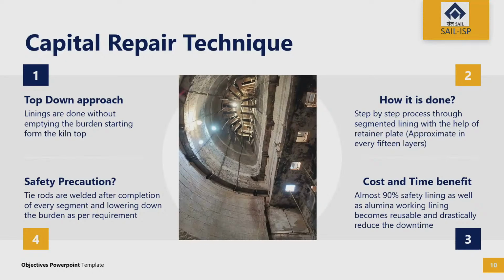So in this top-down process, we do not empty the burden at once. We gradually, step by step, empty the burden and start lining from the top. From the top, we start lining maybe 15 to 16 layers, then we lower the burden and keep on lining, and keep using the old bricks. When necessary, we replace them with new bricks. And in this process, we also have to ensure safety. So we make tie-rod welds. As the picture shows, these rods are welded in several layers using retainer plates. So these also ensure safety, so that as we keep lining downwards, the bricks do not fall down. This also makes it cost effective as we are reusing the bricks.